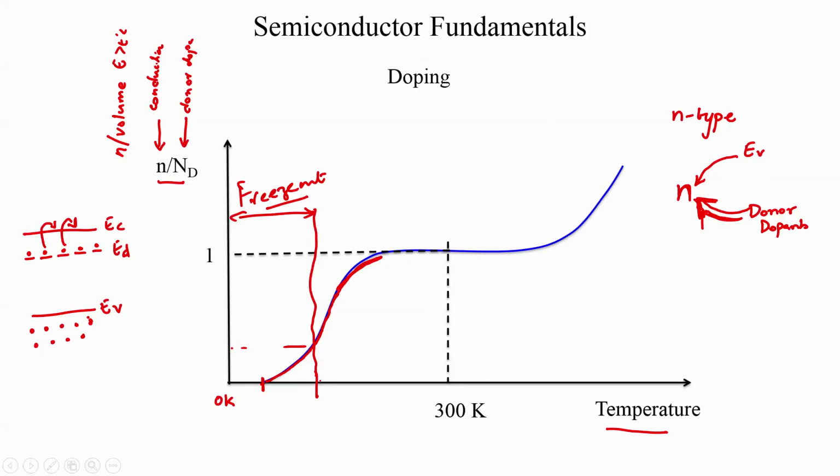So, let us say we had implanted 1E15 donor dopants per cc. At say this temperature, let us say 100 donor dopants were ionized, and therefore, they contributed 100 electrons to the conduction band. And as the temperature increases, this contribution will significantly start increasing. So, let us say here 1E10 donors contributed, and we will reach a temperature where all 1E15 donors will contribute.